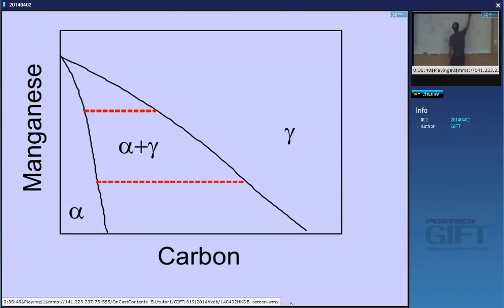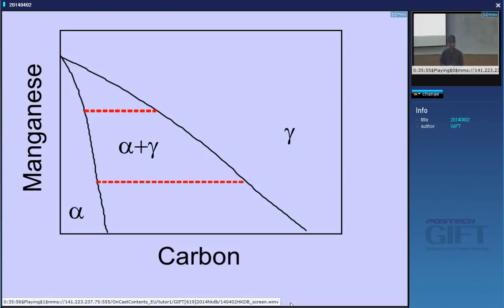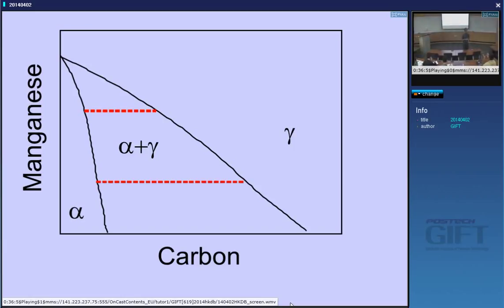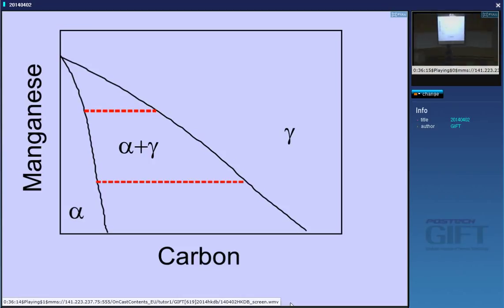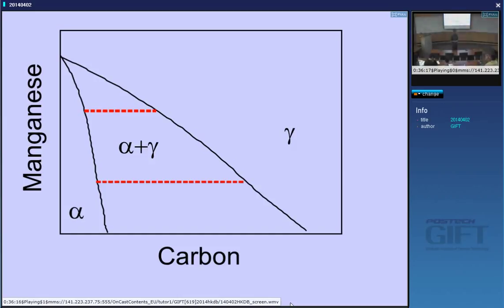Trapping means that the chemical potential of manganese increases when it goes into the ferrite — it doesn't want to be there. Paraequilibrium excludes equilibrium — there simply isn't enough mobility to maintain local equilibrium. What makes an alloy reach equilibrium versus paraequilibrium? Absolutely, atomic mobility. If that isn't there, you cannot have equilibrium.